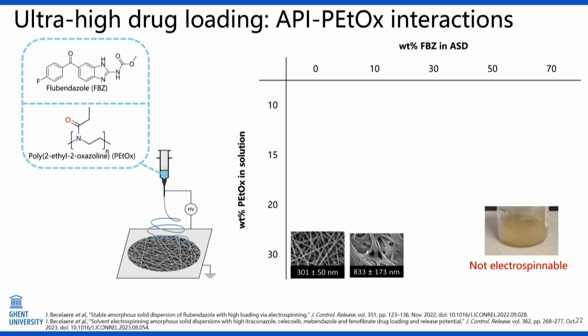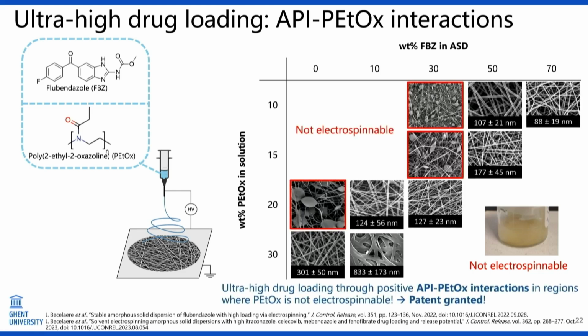But that was due to the interactions, creating a high viscosity and giving it a difficult processability. Then the trick was to reduce the amount of polymer to very low amounts, which are normally not electrospinnable, but because of the interactions, if we use a lot of drug, the rheology is sufficient again for spinning, and we could go up to drug loadings of 70–80%, depending on the API.